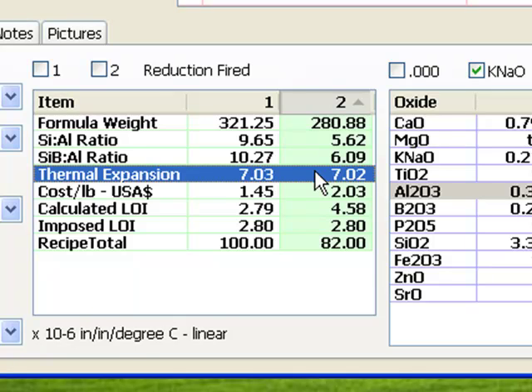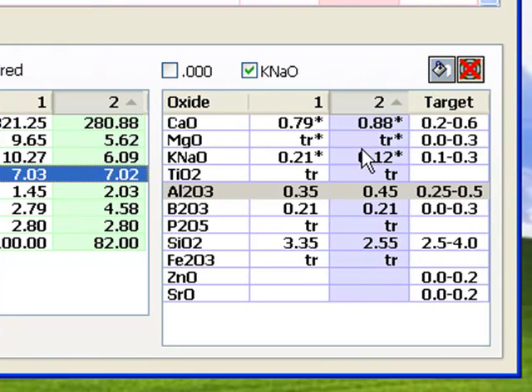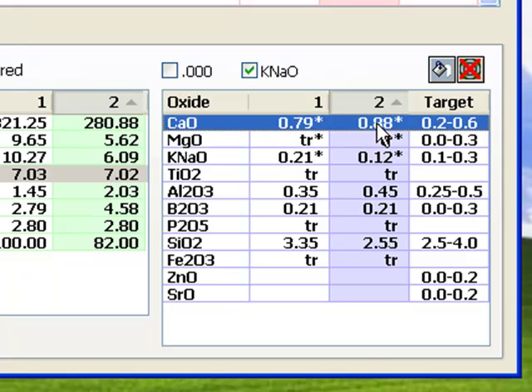It's actually possible to take the expansion a lot lower than this by sourcing MgO from dolomite or talc, or better yet, a frit at the expense of CaO. But this should not be necessary. This should fit just about any body that I use. I could increase this CaO even more to grow more calcium silicate microcrystals on cooling to get an even better matte. This would require care to be sure the glaze was not soluble.